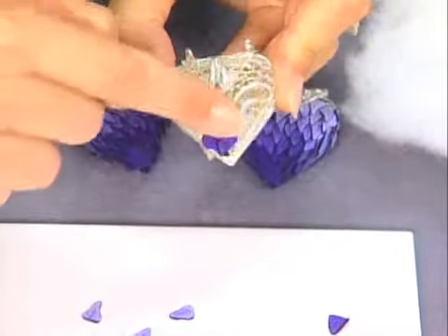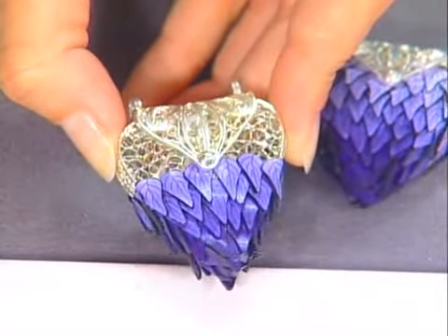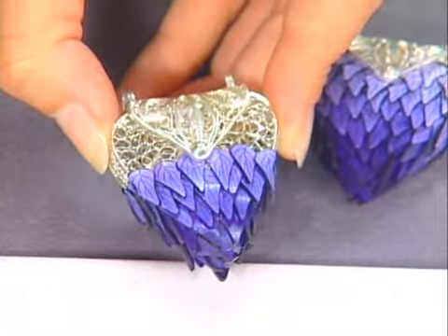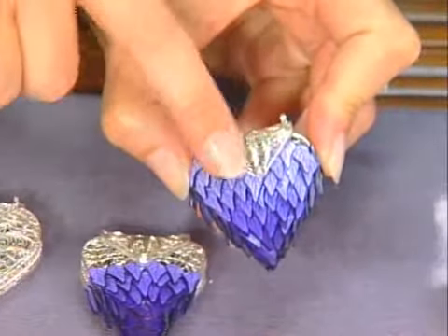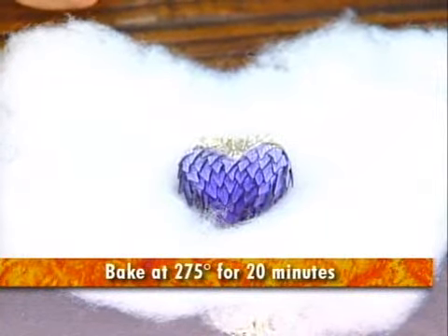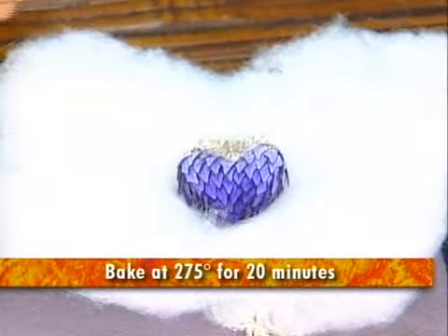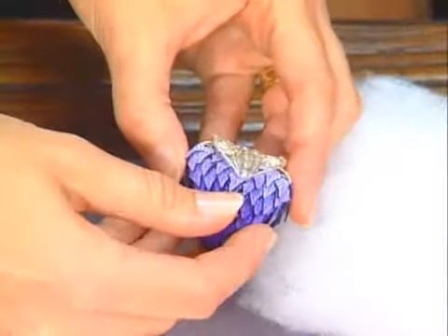Look at how easily they stick. You just press on the top and it gets down into those little grooves. We're going to build layer upon layer — you can see the gradation as we've gone through our cane slices. When you get to the top and start putting more on, if you hold it while it's still raw it can affect the shape, so go about this far, leave the flap open with a little spot to hold it. Then put it on a piece of cotton batting and pop it in the oven at 275 degrees for about 20 minutes. This metal purse can go in the oven absolutely — because it's such a low temperature it won't affect it at all. After it cools, you can hold the piece. You want to let it cool — that's right, after it cools it's totally cured.